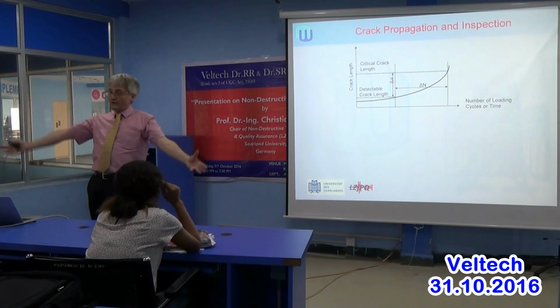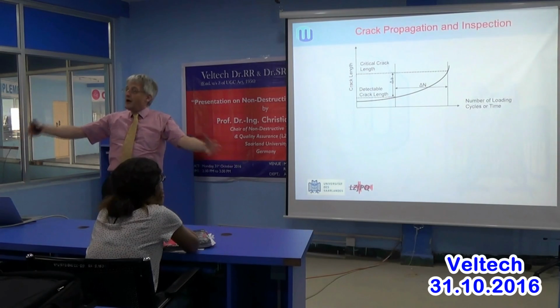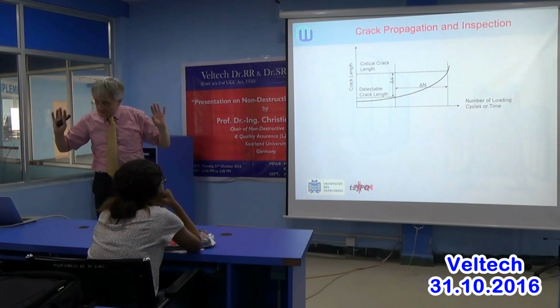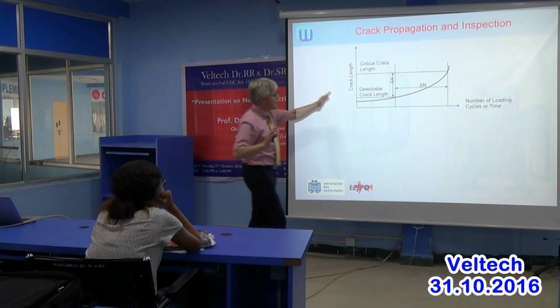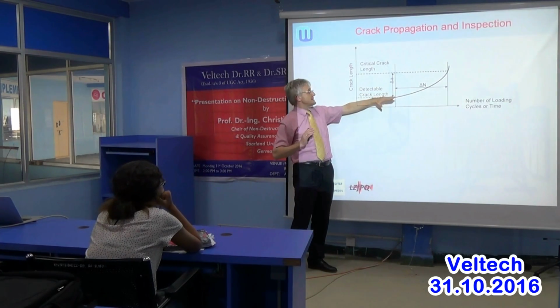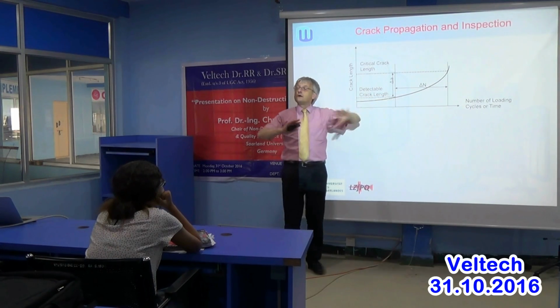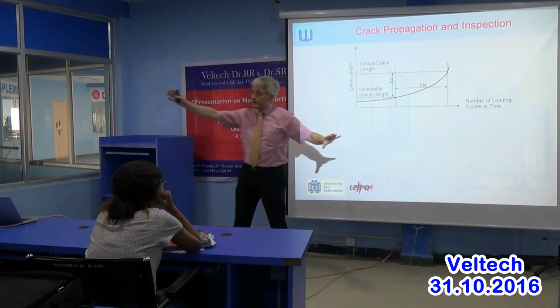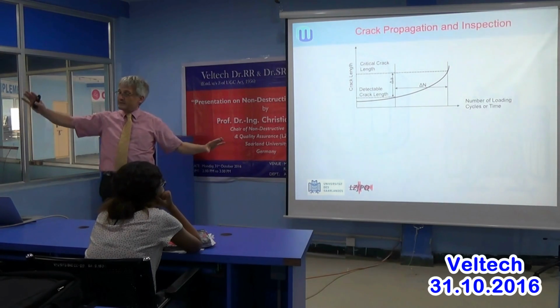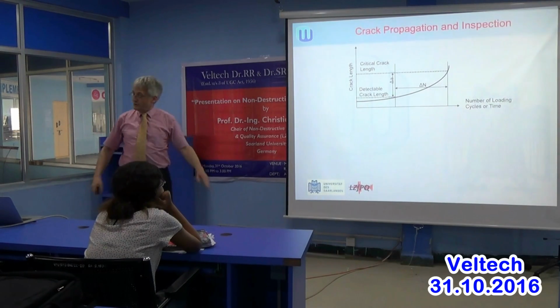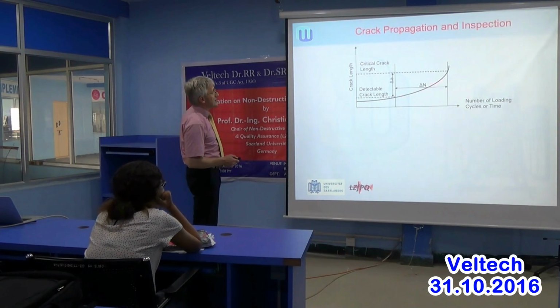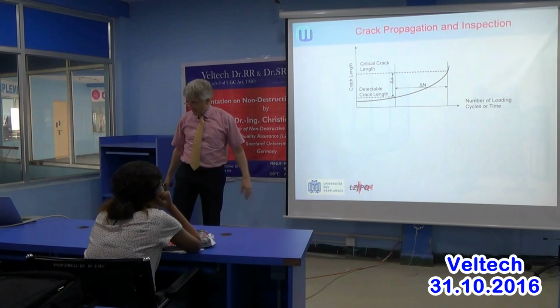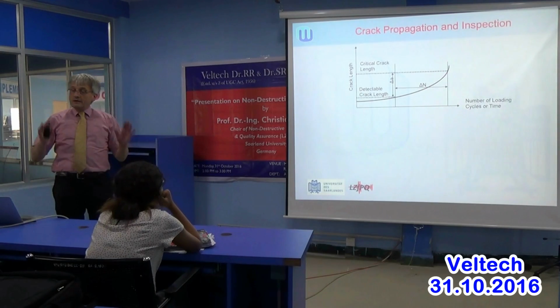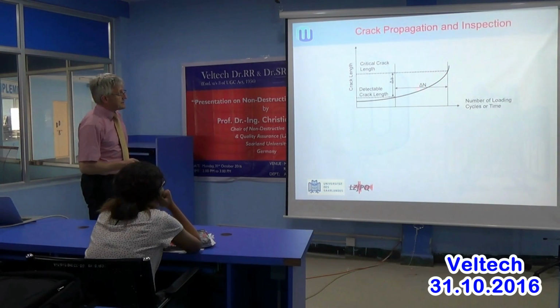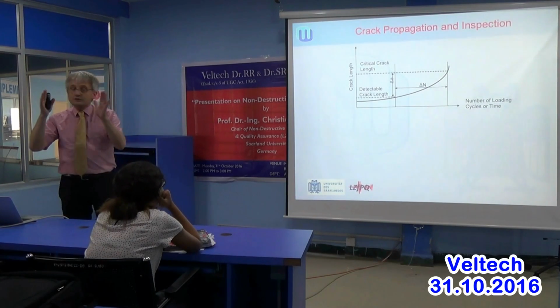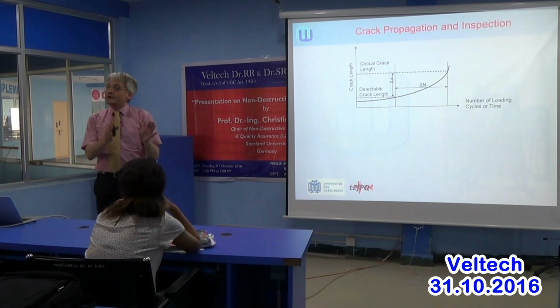So if we inspect the structure, then we'll say, okay, we haven't seen any crack visually or with whatever technique we have used, and we know there was definitely no crack which was bigger than this crack. So we assume in our crack propagation, this is the crack which we might have in our structure. And now we get the plane flying, and the question is how many flight cycles, how many flight hours is the plane allowed to fly? And from calculation we get a certain number of flight cycles, that's what delta N says. And then we say, okay, so you need definitely to inspect before you have the number of delta N cycles. And usually, because we're good engineers, we say take half of it and look after half of it.